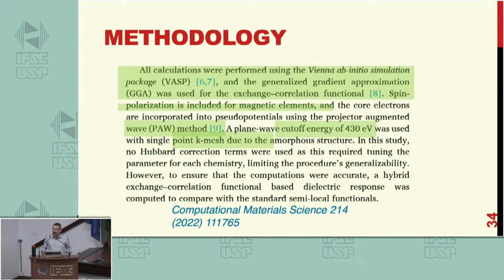This is very interesting. When you work with solids, with crystals, we usually look for the properties in reciprocal space, okay? And all these codes that I told you, they all do the calculations in reciprocal space. Then you said, okay, but glasses, we don't care about the reciprocal space. There is no periodicity. When you have a crystal, you Fourier transform it and you go to reciprocal space, momentum space. And for glasses, it wouldn't be needed.